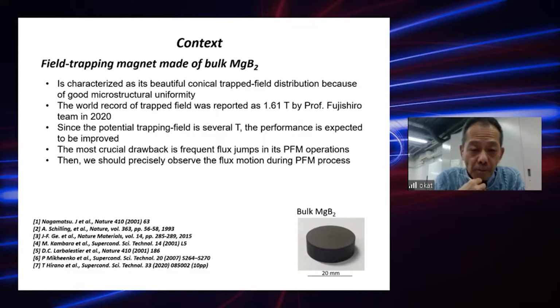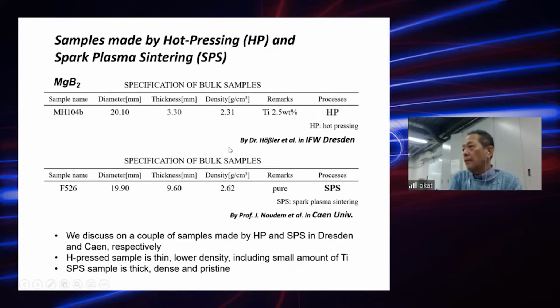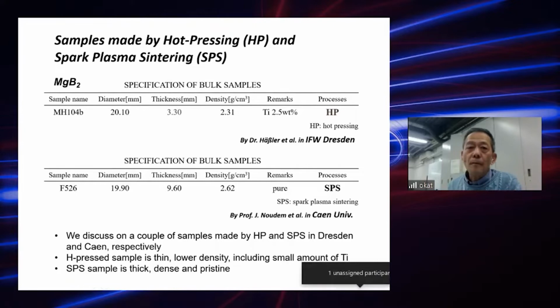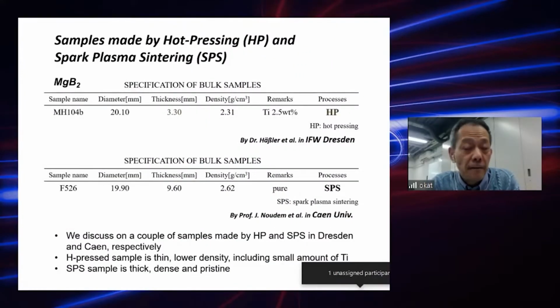The most crucial drawback is the frequent occurrence of flux jumps in PFM, pulsed field magnetization operations. Then we should precisely observe the flux motion inside the bulk during PFM processes. The samples were made by hot pressing and spark plasma sintering. One was made by Dr. Hässler at IFW Dresden, and the other is provided by Professor Noudem at Caen University in France.